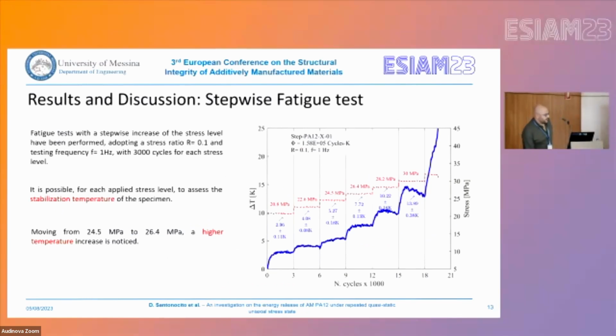In order to validate this value, we move to the stepwise fatigue test. We increment the applied stress level. Here you can see the variation in the temperature signal with respect to the number of cycles, and we record the stabilization temperature for each stress level.